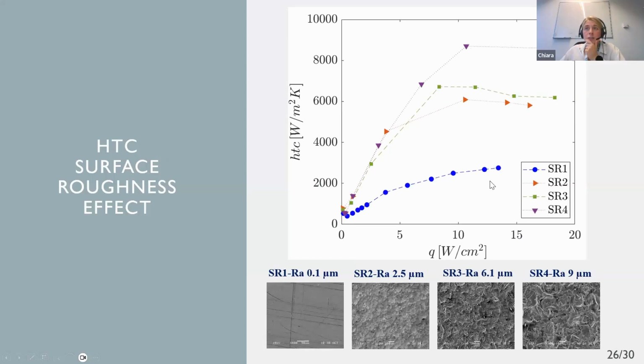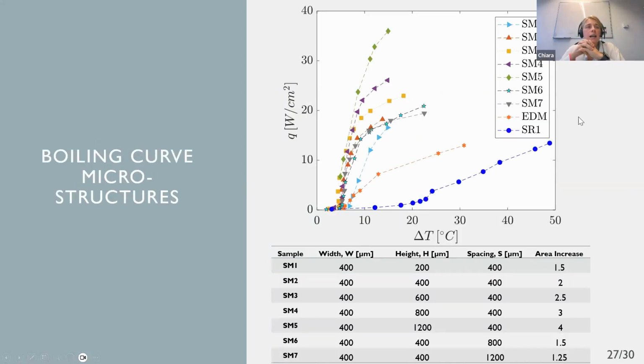The effect of roughness is also visible on the heat transfer coefficient curves. So we can see that the heat transfer coefficient for a given heat flux, so for a given dissipated power, increases almost 4 times simply by increasing the surface roughness. Very similarly, we can analyze the boiling curves of the microstructured samples. Below you can see the different heights and spacings that we tested. Of course, increasing the height or reducing the spacing increases the overall heat transfer area of the sample, and this is one of the main driving factors for which the heat transfer is improved.